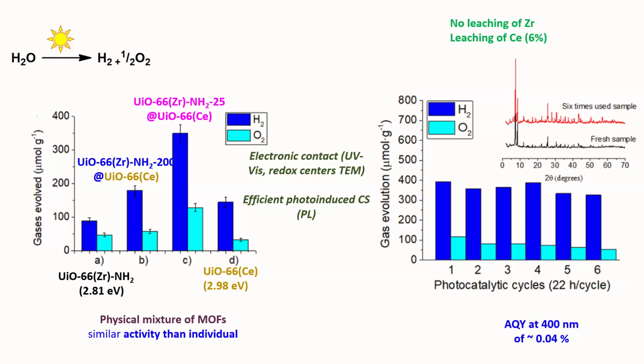And also the electronic contact between these 2 solids was confirmed by UV-visible and redox test and by TEM analysis, and the efficient photo-induced charge separation was confirmed by photoluminescence spectroscopy.